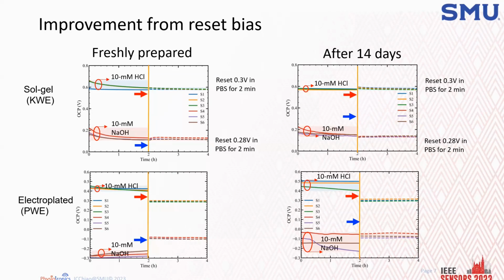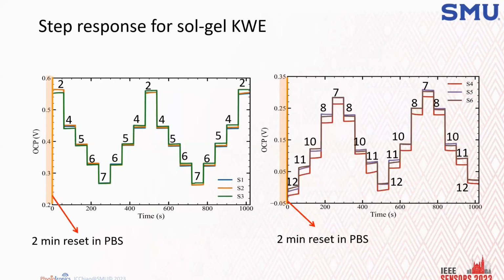So we believe that the reset bias can improve the drift issue. But how does that do for the sensitivity and hysteresis? So for sol-gel electrode, we do the stepwise measurement. We reset, and then we do 1 cycle and 2 cycle. 1 cycle from 2 to 7, 7 back to 2. And the other one is alkaline from 12 to 7 and back to 12.